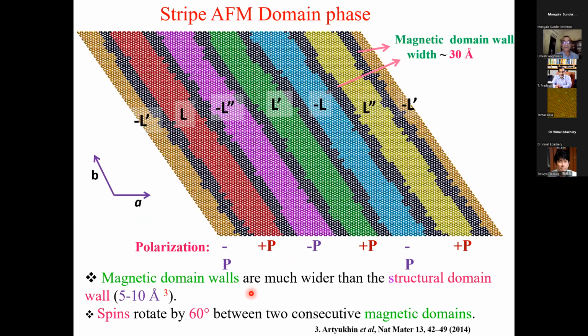And then we also simulated the domain structure in these materials. Of course, the domains are very rich. In fact, domain structures in ferroelectric and ferromagnetic materials have been studied very extensively, but not quite so in antiferromagnetic domains. So these are some of the first simulations where realistic domain structure is simulated. And you will see the domain walls are quite wide, about a few nanometers, and spins rotate by 60 degrees when you go across a domain wall.